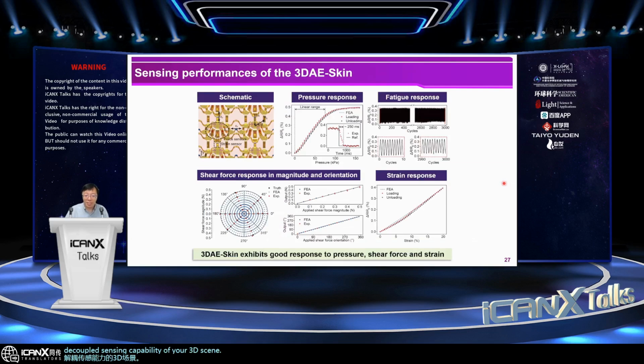Okay. This slide illustrates the characterization of the sensing performances of the 3DAE-Skin. The image on the top middle shows the pressure sensing results. You can see a linear range of around 80 kilopascal and a response time of 250 milliseconds. After 3,000 cycles of pressure loading and unloading, the sensing performance is still very reliable. If you look at the results on the bottom, you will see the results of shear force loading along 6 different directions.